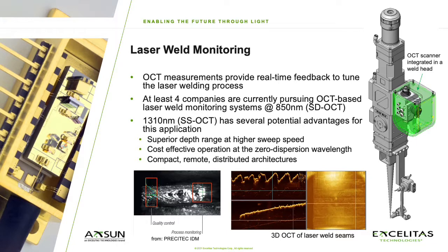Monitoring of the laser weld process by OCT can generate a variety of metrics that predict the quality of the weld, such as the seam profile ahead of and behind the weld, as well as the penetration depth of the keyhole during the weld. This is achieved by attaching the OCT scanning apparatus to the weld head camera port and introducing the image beam using a dichroic mirror.